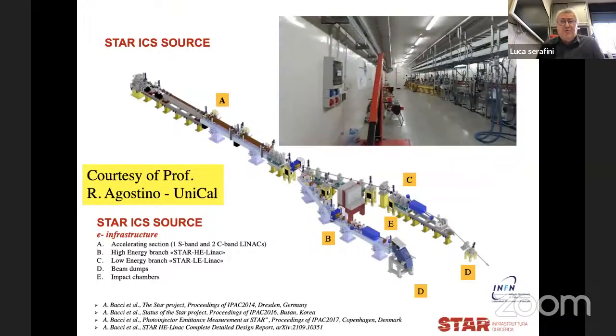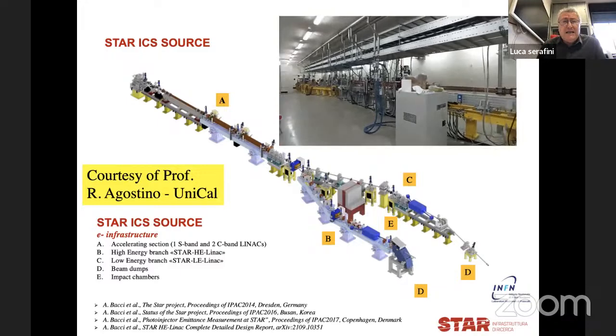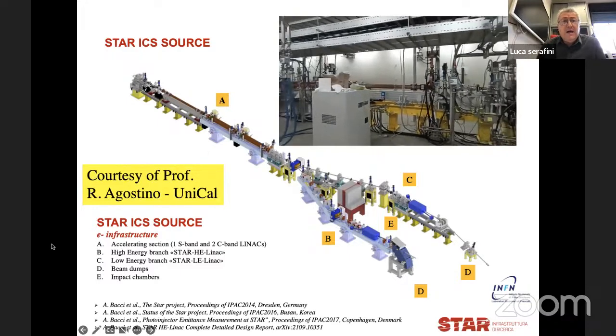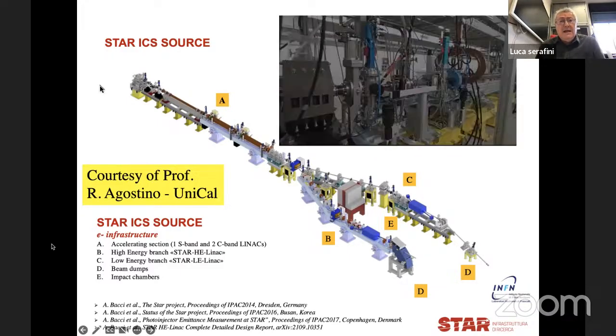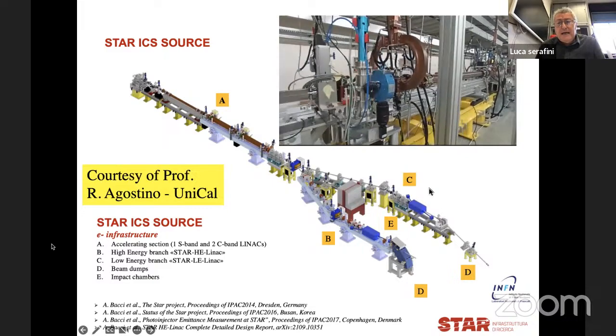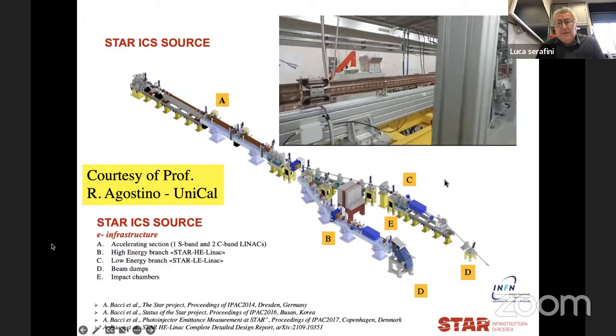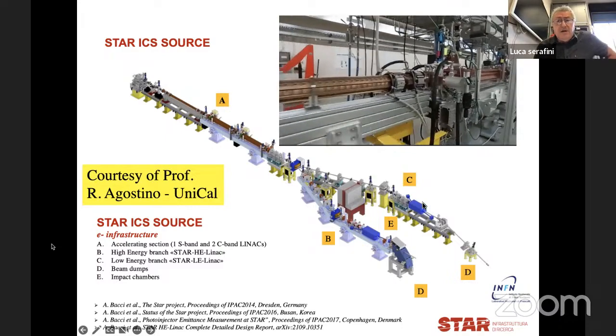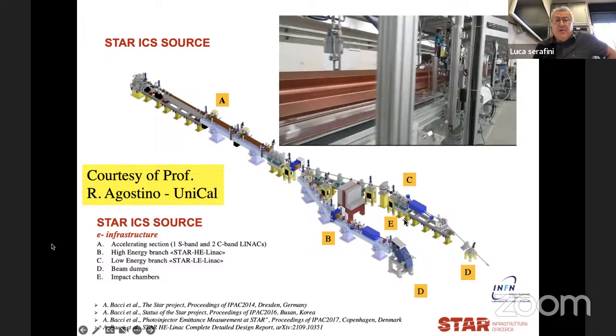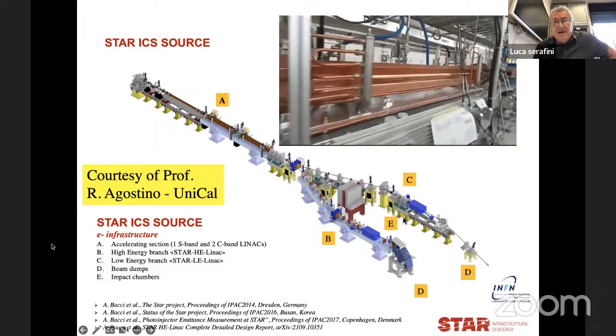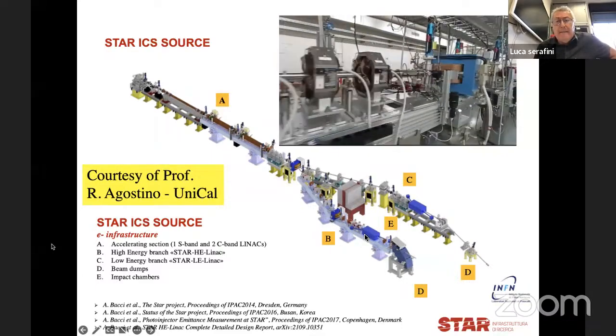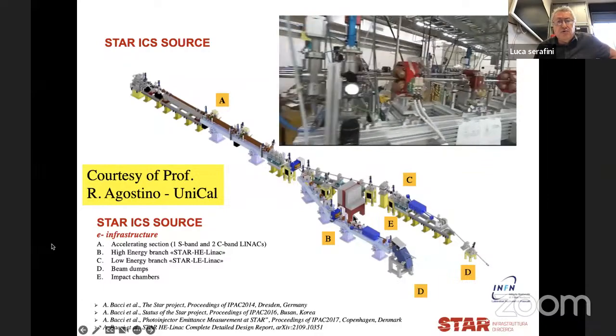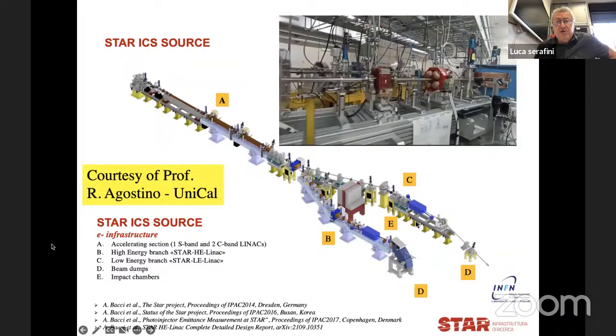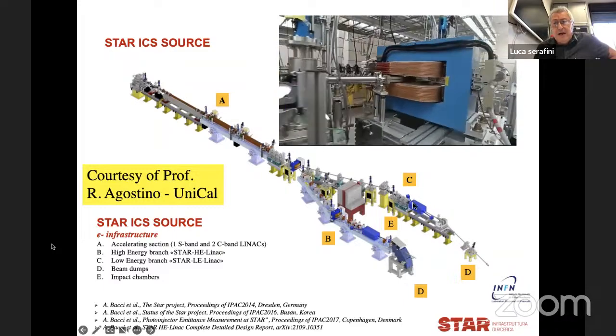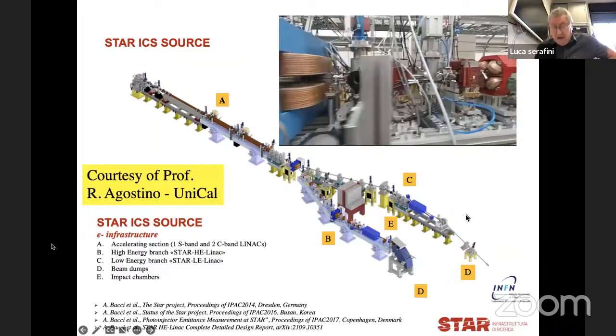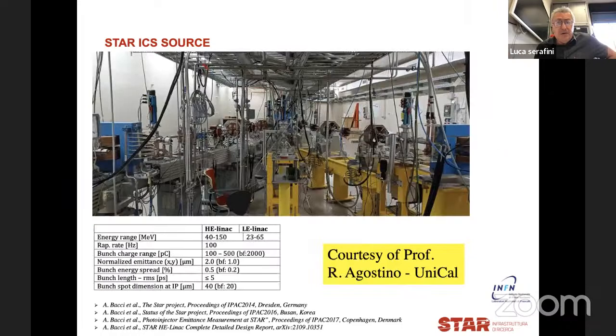If you look at the video, it will give you a view of what is inside the bunker. And inside the bunker, we have a 150 MeV LINAC driven by a photoinjector with 2 beam lines, 2 independent interaction regions where the ytterbium YAG 1 joule, actually 500 millijoule, interaction laser is brought to collision with the electron beam. And so there are 2 beam lines. You see one for high energy and the second is for low energy. Let me go through quickly.